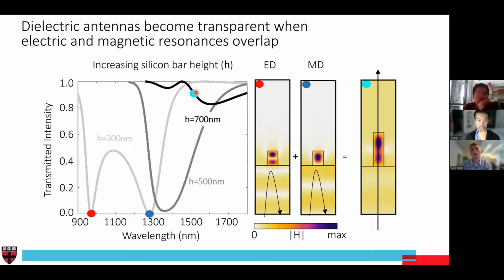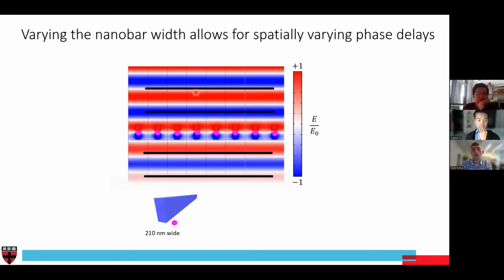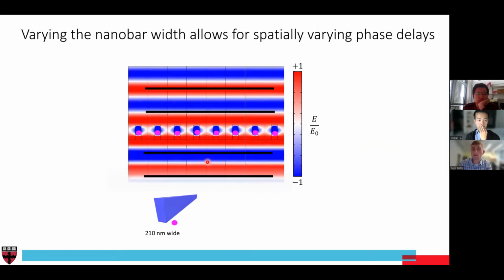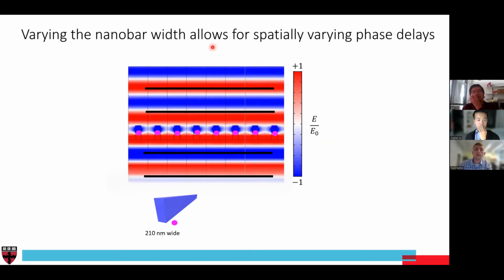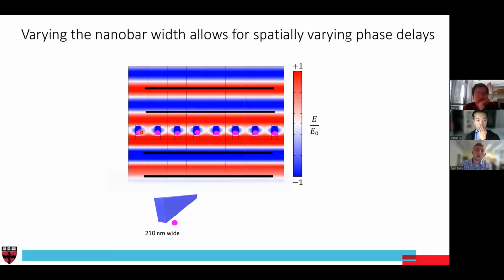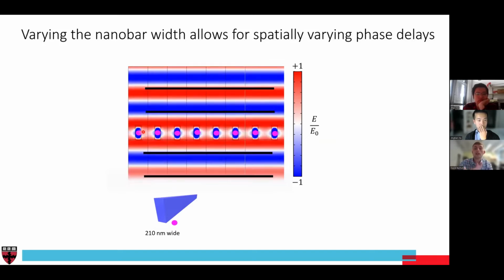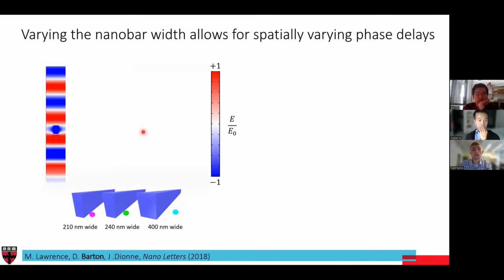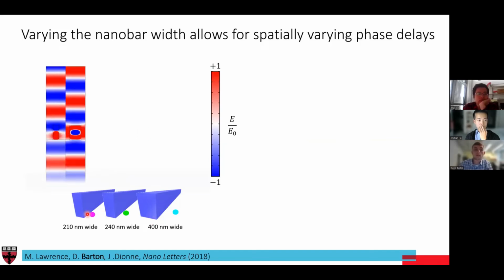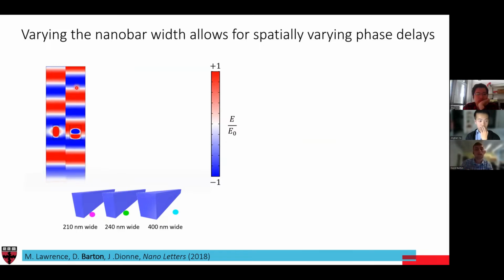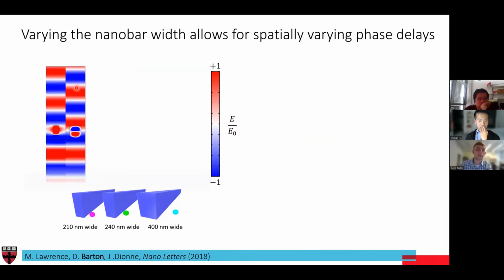We can go one step further. If we have these tall nanostructures, now I'm showing a simulation of light propagating through the bottom, up through these silicon antennas, and then coming back out the top. If we change the width of these bars, we engineer what happens to the scattered phase. In this example, if I have 210 nanometer wide nanobars, and then I put them next to bars of different widths, you can see that the light that is exiting has a difference in the total phase. This red part, the peak of the electric field, is slightly different than the neighboring element.